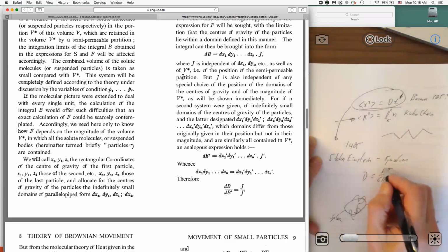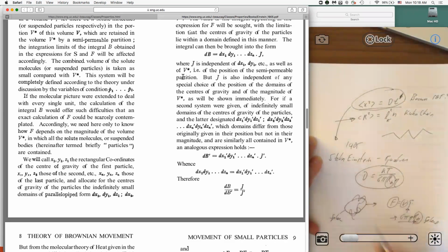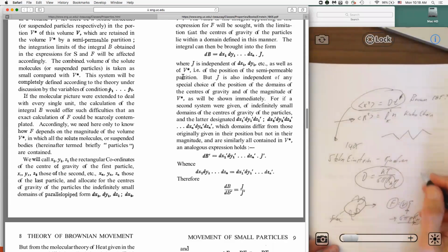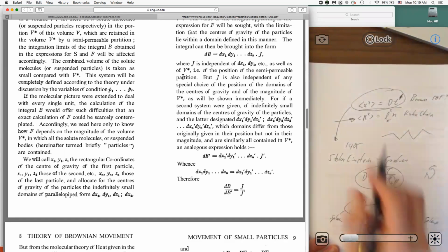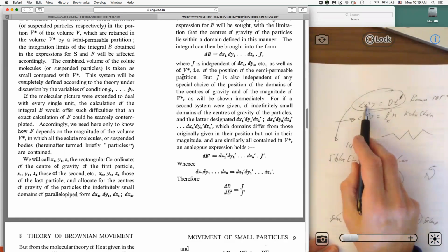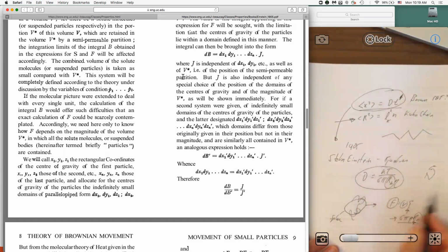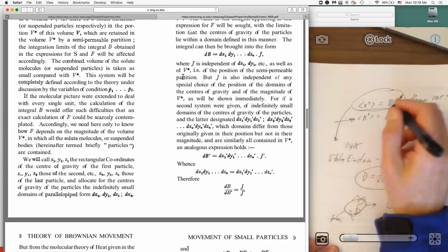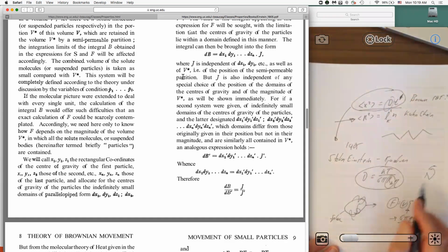This equation becomes important for things like dynamic light scattering, where you look at the motion of particles in space and the diffusive motion. We follow this kind of equation, where the distance they travel goes to the square root of time, and from that you get the diffusion coefficient. What you want to get from that measurement is the hydrodynamic size, the equivalent spherical size of an object that has the same drag coefficient.